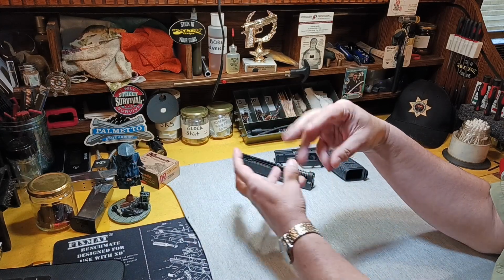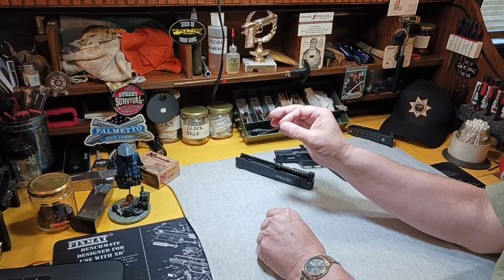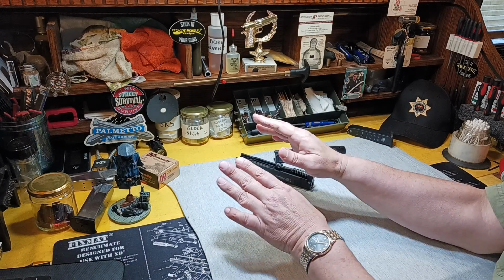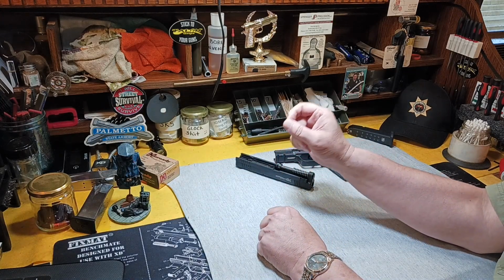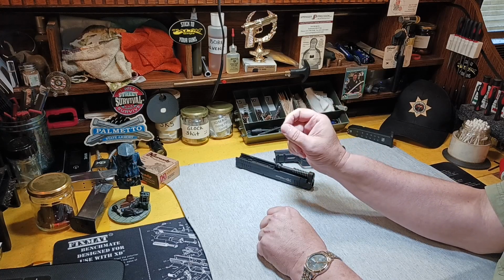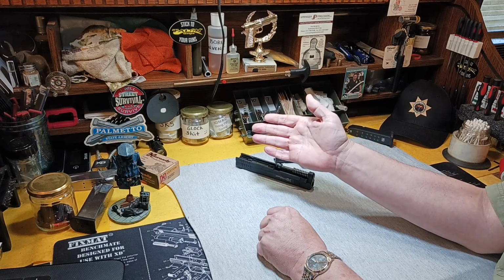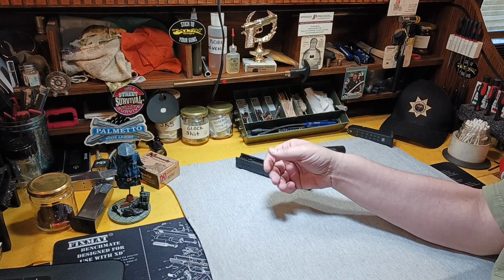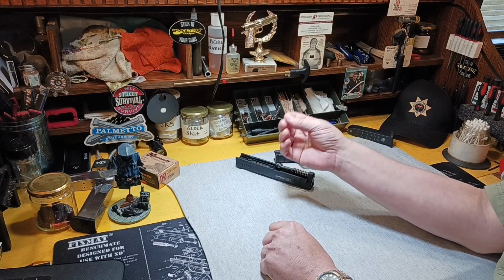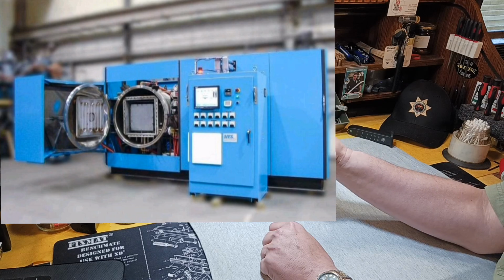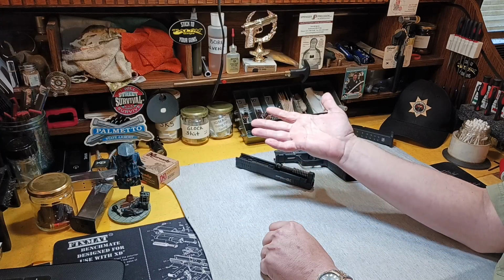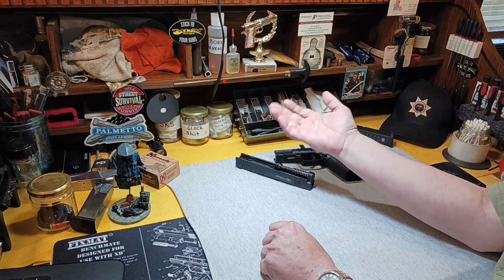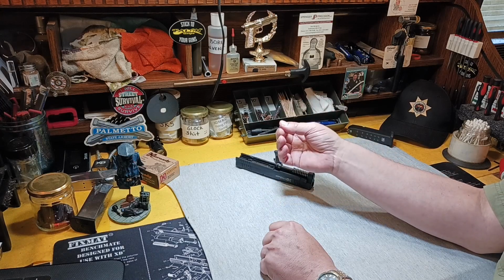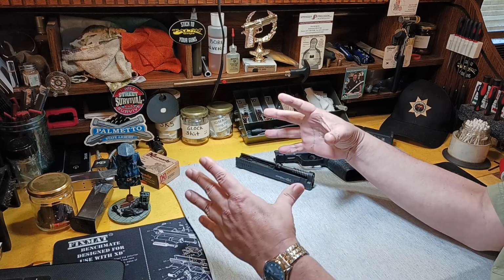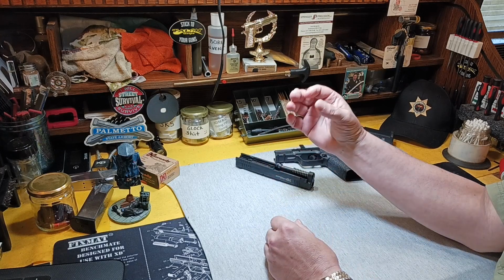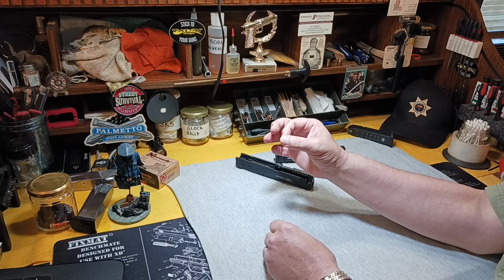All right, now this slurry is injected into a heated precision mold, and it will form what is called a green part. Green being new. Now, that green part is 20% larger than what the final finished part will be. But in that green condition, it's still in its embryonic stage, and so it will snap under finger pressure at that point. But once cooled, that part is placed into a sintering furnace with dry hydrogen gas and then heated to a temperature of some 2300 degrees, or just below the melting point of the particular metal used in it. In this process, the binder will vaporize and the powdered steel will fuse together. It'll bond together, and the part itself will shrink by 20% to its final and correct dimension.